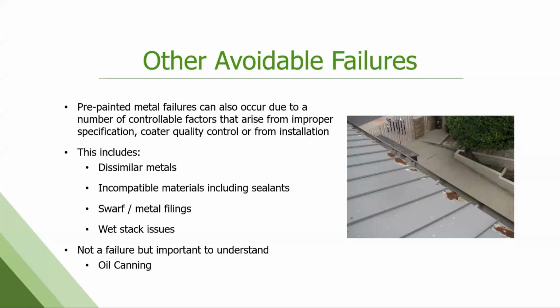Using wrong sealants, leaving swarf, which is metal filings from the drilling process or cutting on site that takes place in these panels. That rust leaves a stain on the surface. Wet stack, this is storage corrosion. So the panels, when they're stored prior to installation, if moisture gets in between those panels and they're not allowed to dry out, you will get premature corrosion starting underneath the paint system. Paint system then comes off once it's installed. Looks like a failure. Oil canning, not a failure, but it does happen on light gauge rolled steel products, which is kind of that buckling or wave that you might see in certain panel designs after installation.